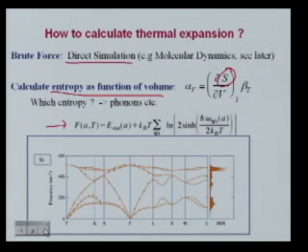You know, this looks hard, but phonon calculations have become quite routine. They're very well developed. There are in some cases even codes that do it almost semi-automatically. It's typically done either by linear response techniques, or where you perturb a lattice literally by a phonon with short wavelength so that you can calculate the energy of it. So it's literally like setting up a supercell with a phonon in it. It's called a frozen phonon approximation. There are perturbation techniques, linear response techniques, and then some people do it in real space by calculating force constants and setting up force constant models for phonons.